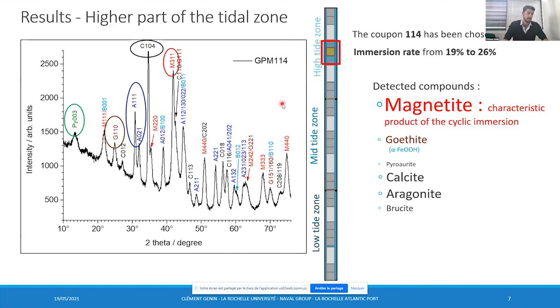And here, magnetite is a main compound detected, which is a characteristic corrosion product of the cyclic immersion. Goethite too is detected, which indicates large flow of dioxygen, and pyroaurite again. Calcite is still detected from the shells. Aragonite and brucite are again detected, which indicates that cathodic protection is still a little bit efficient here. But there is an opposite ratio.